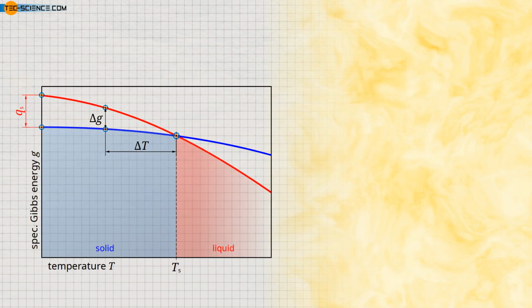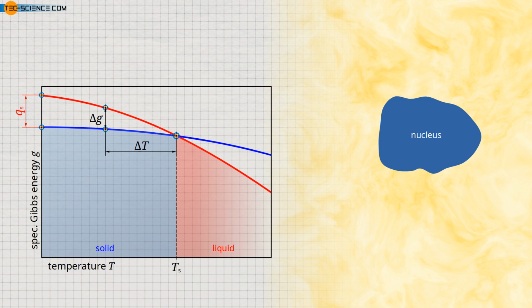Although supercooling is now in principle a drive for phase transition and the process strives to run by itself, it does not take place spontaneously. This is because an important influencing variable, which also affects the Gibbs energy of a solidifying nucleus, has not yet been taken into account. If a nucleus is formed in a melt, it obviously has a solid surface. Energy is required to form such a surface due to the attractive forces on the nucleus surface. This is called surface energy, which is required for the formation of the solid surface during crystallization.